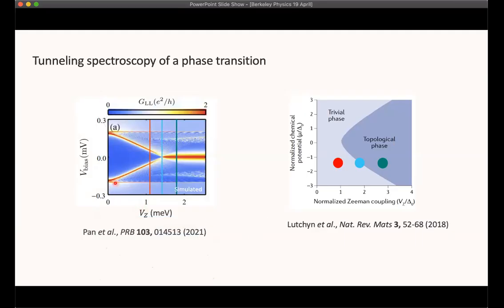And so this is a simulation showing exactly that. So if you tune the Zeeman energy, the expectation is there's a gap observed in tunneling spectroscopy. It closes at the phase transition here, and then it reopens very faintly. And at zero energy, there's a very well-defined peak in conductance indicating the presence of a Majorana.